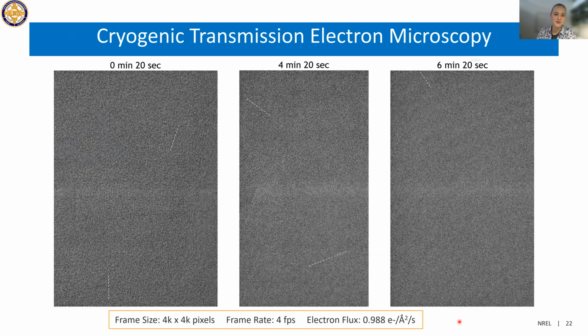We also were able to do some more high resolution imaging using these cryo holders and a direct electron camera. And so we were able to do a very low dose of the electron beam over the sample. And then you could see that these lines just highlight some of the lattice in the lithium metal that was imaged under the electron beam. And so the tools really matter for getting good characterization out of these battery electrodes. And so this is why doing it at certain sites makes a big difference.